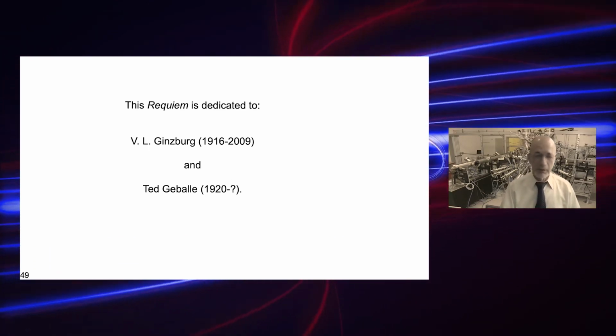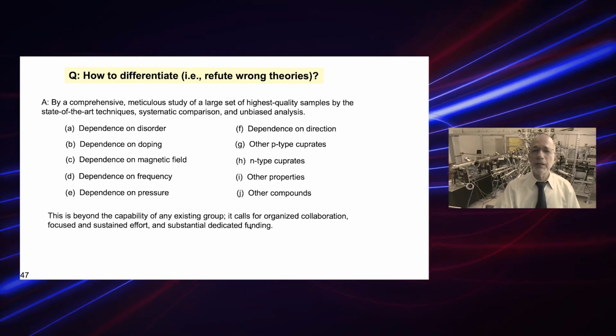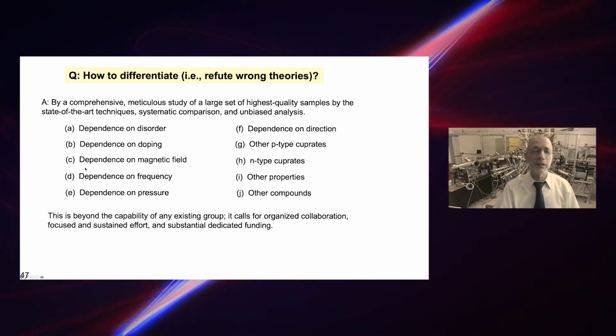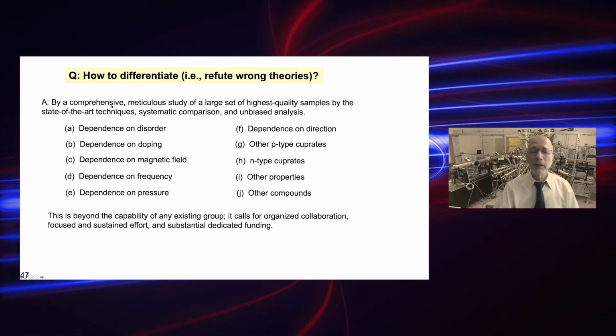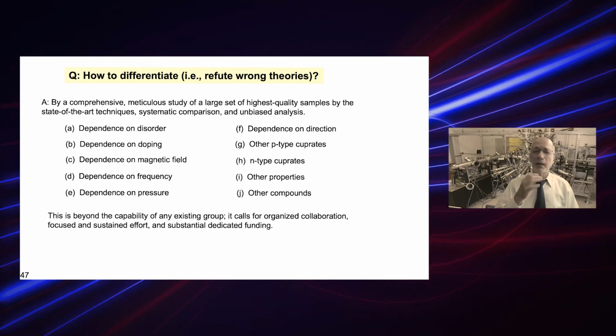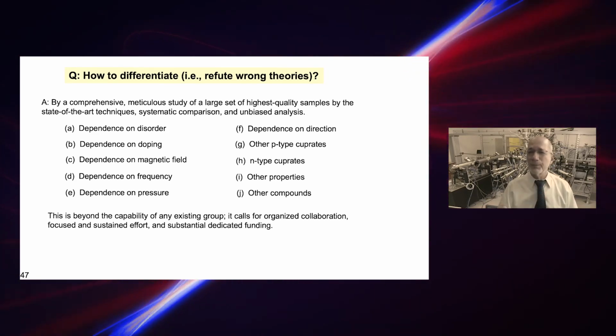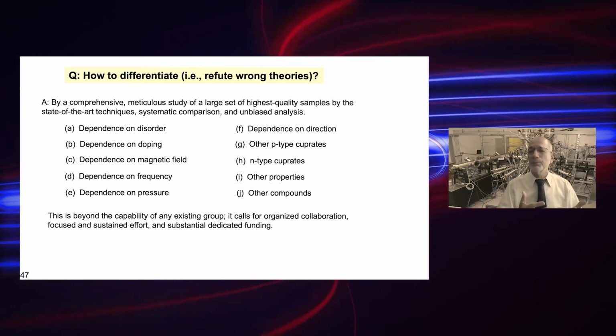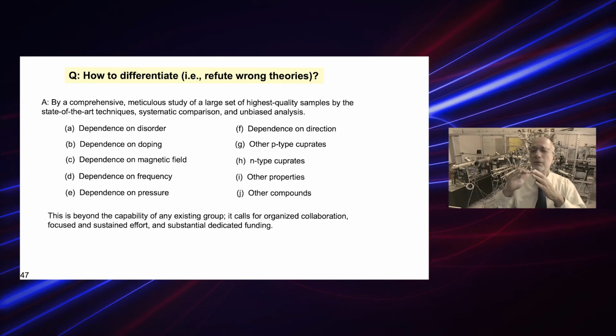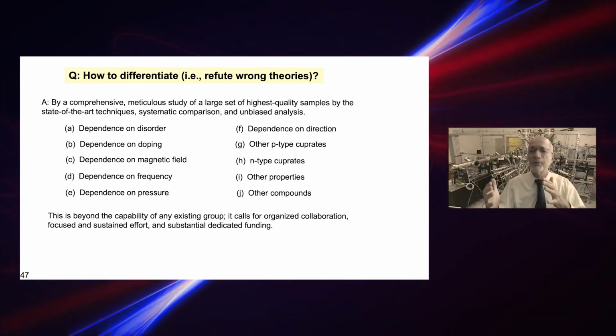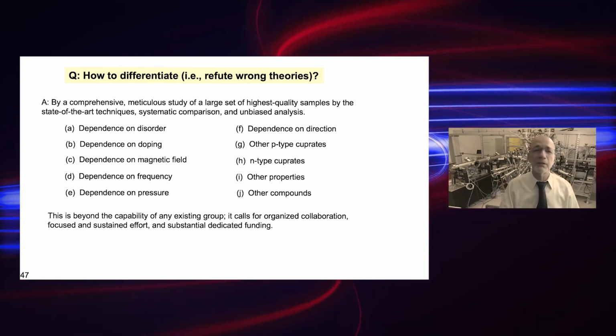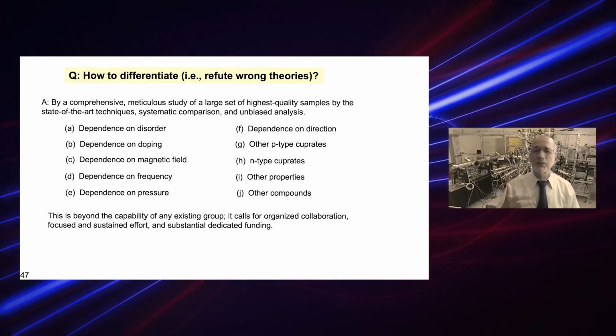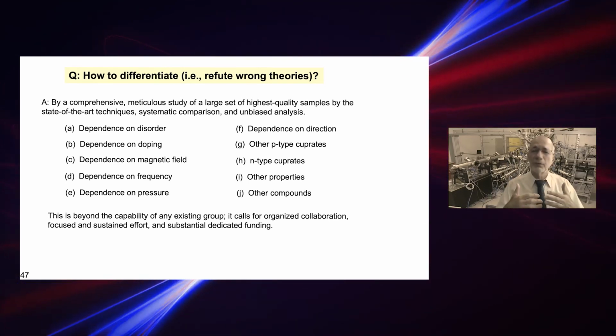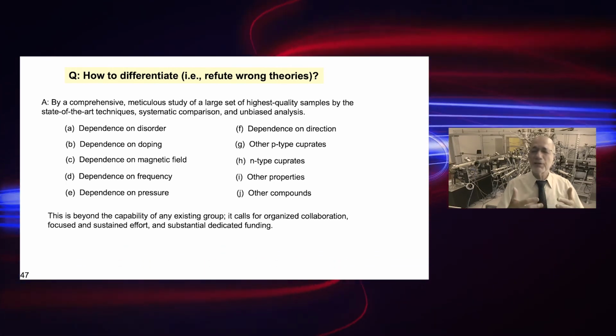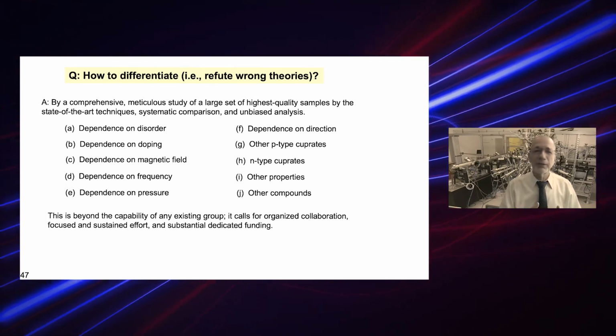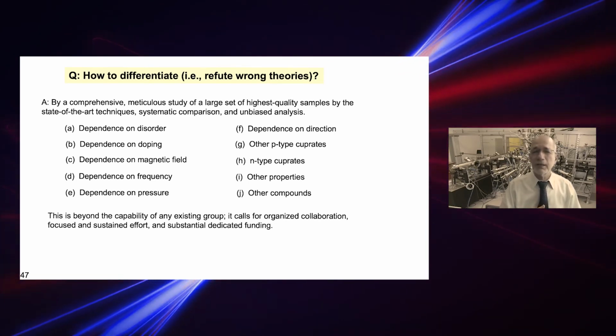As I said, the key of what I was trying to say is this line A, which is the answer. We need a comprehensive study, and in my language that means 1,000 samples, 3,000 samples, not one sample. That's how we studied, for example, the superfluid carrier density and resistivity and magnetoresistance. Second, you need samples of the highest quality, to reveal the intrinsic properties, so that you're not masked by defects. Then you need state-of-the-art techniques.